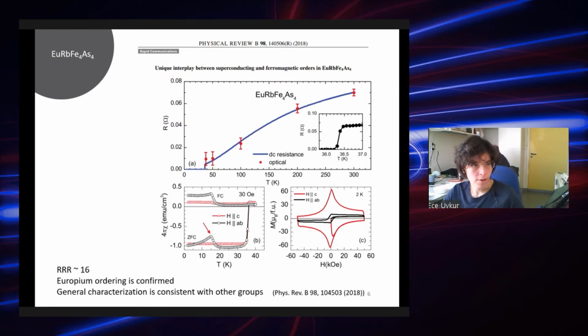Now the results are based on the manuscript that was published a very long time ago, but maybe now it's time to discuss the details a bit more. This was just the characterization of our sample, and back then it was consistent with other groups, meaning there was another publication on single crystals, and it was consistent with that group. We quite nicely see the europium ordering, and the resistivity of the sample used in the optical spectra was quite nice. The RRR ratio was quite high, the transition temperature showed a 36 Kelvin transition, and everything seemed to be nice.